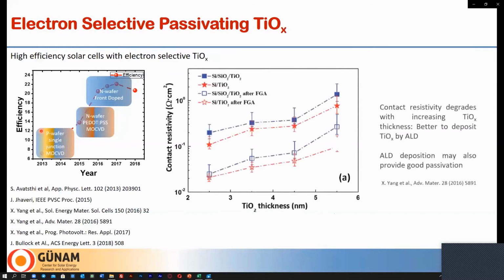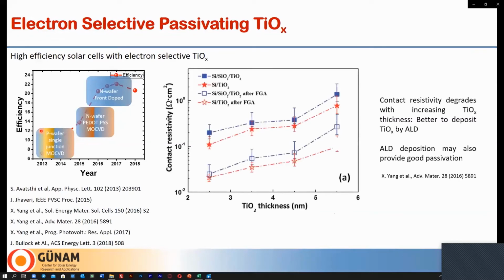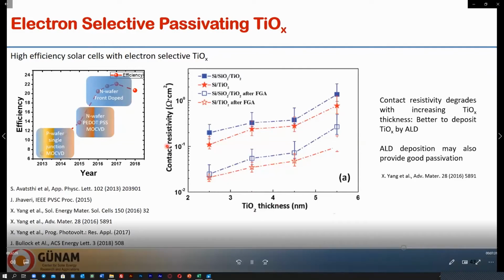One of the important parameters of titanium dioxide is its thickness, and you can see in this study they found that when increasing the thickness of titanium dioxide, the contact resistivity increases. This requires good control over the thickness of titanium dioxide, and this can be done by atomic layer deposition. With only a 1 or 2 nanometer change in the thickness of titanium dioxide, the contact resistivity increases, affecting the performance of the device.